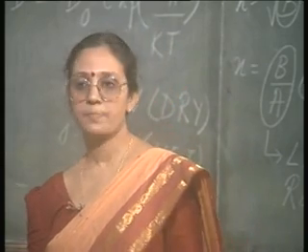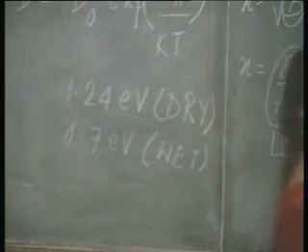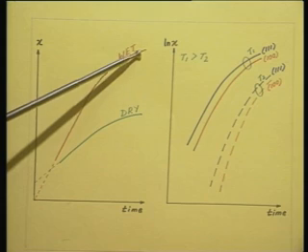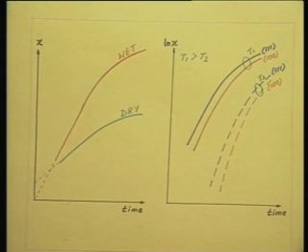However, experimentally, both these curves are experimental curves, right. Experimentally, when you generate this curve and then try to extrapolate it, you find that even though the wet oxidation curve passes through the origin, the dry oxidation curve does not pass through the origin.